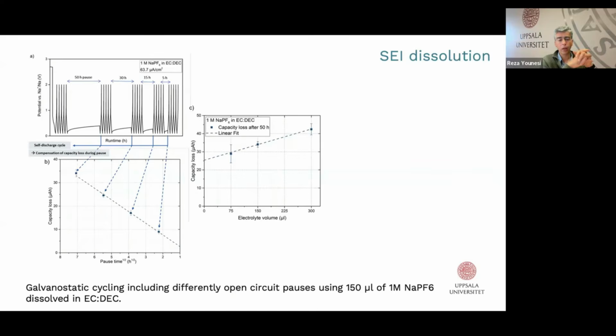Basically, when we give time, some SEI species dissolve back and diffuse into the electrolyte solution. On the right, we can see that this capacity loss is related to the volume of electrolyte. There's a linear relation between the electrolyte volume and capacity loss, which again confirms the idea that part of SEI is dissolved back into the liquid electrolyte. The larger the volume of electrolyte, the more SEI is lost into the electrolyte solution, which makes sense.